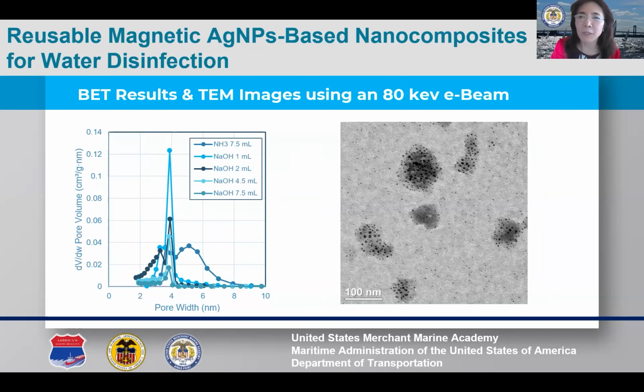In our initial proof of concept work, we used ammonia as the base catalyst, as is common in the Stöber method. The resultant nanocomposite was labeled ammonia 7.5, with 7.5 representing the use of 7.5 milliliters of silica precursor, TEOS. Later, due to concerns that ammonia might etch the coated silver away because of its complexation with silver ions, we switched to sodium hydroxide as the catalyst. With sodium hydroxide, we varied the amount of TEOS to explore the control over channel length and the silver release rate, producing nanocomposites named sodium hydroxide 1 through 7.5, where the number indicates the TEOS used.